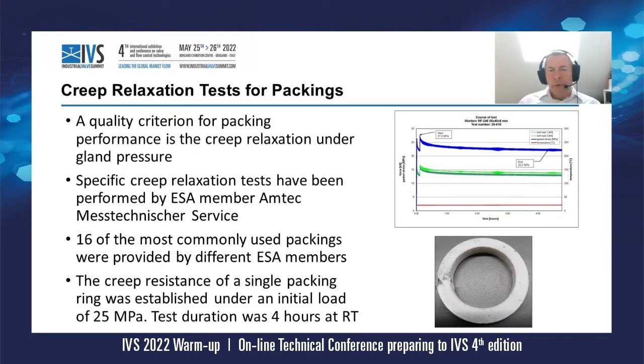So we set up a test, and 16 of the most commonly used packing materials were defined and provided by different ESA members. The creep resistance of a single packing ring was established under an initial load of 25 MPa. The test duration and holding time was 4 hours at room temperature.